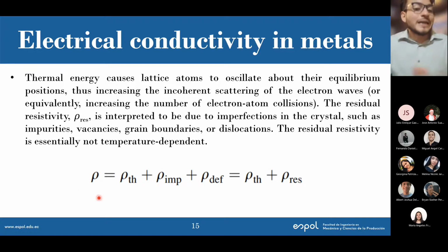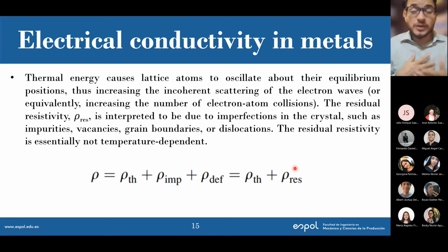So the resistivity of a metal in general is composed of these two terms: the thermal resistivity, that is obviously dependent on temperature, and the residual resistivity, that is just the addition of resistivity caused by impurities and defects, defects being grain boundaries, dislocations, whatever you want to call them. Those terms obviously don't depend on temperature. At least one can safely argue that they don't, even though you could argue that if you increase the temperature, you might reduce the number of dislocations and therefore the resistivity will decrease. Yes, but that's sort of pulling the rope too far.